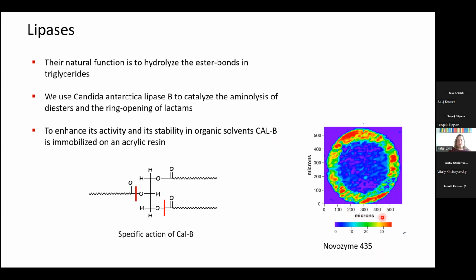And yeah, we worked in this field of enzyme immobilization for a while. But then, you know how research goes. Then you diffuse away, or you don't find follow-up money. But I still find it an extremely interesting research field, and I follow the literature, and it's really amazing what other people find in terms of stabilization of enzymes just by attaching it to a surface or putting it into a pore, and then all of a sudden it's 100 times more active and survives 150 degrees in toluene. So there's a lot to gain also in this research field.